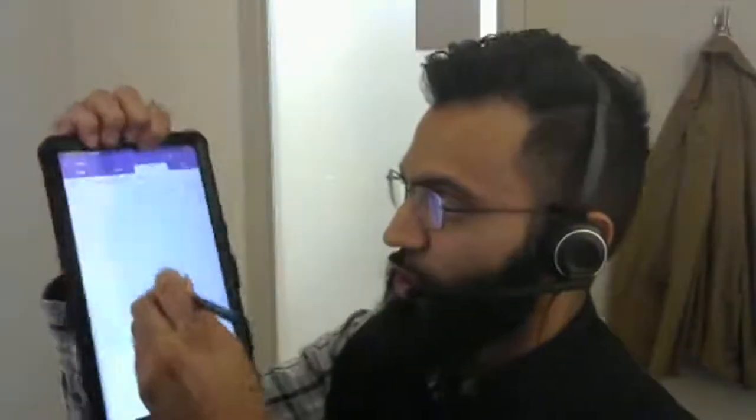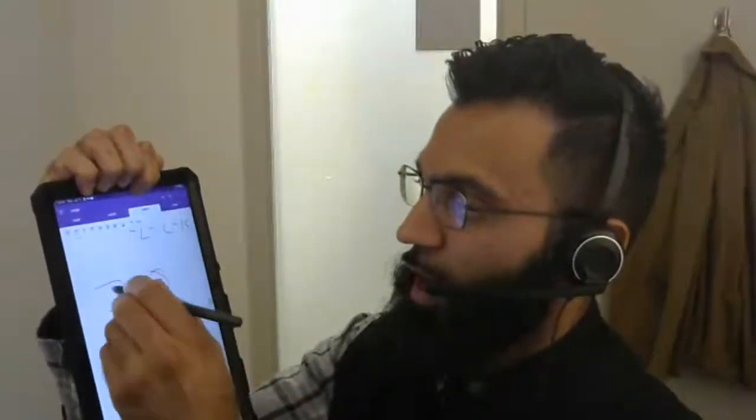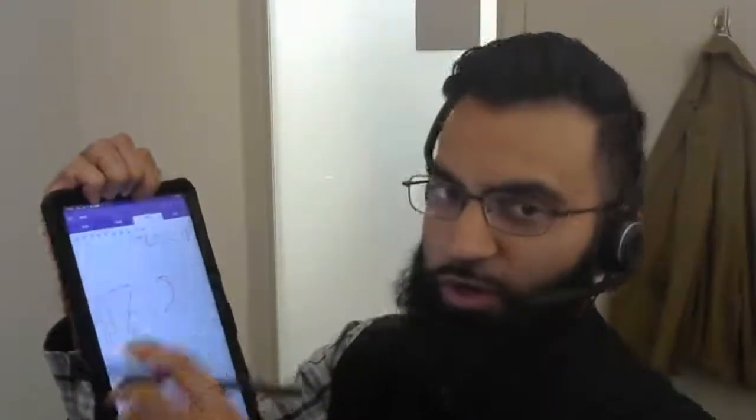Welcome to episode number 70 of the Piezo SHOCK Show, and today I'm going to be answering a question from a viewer like you regarding one of my previous webinars where I modeled a piezo material, which is anisotropic by definition, as an isotropic material in order to easily simulate that and not have to worry about putting all these different properties in. All you have to do for an isotropic material is know its density, know the Poisson's ratio, which most of the time you can assume is like 0.3, and know the modulus.